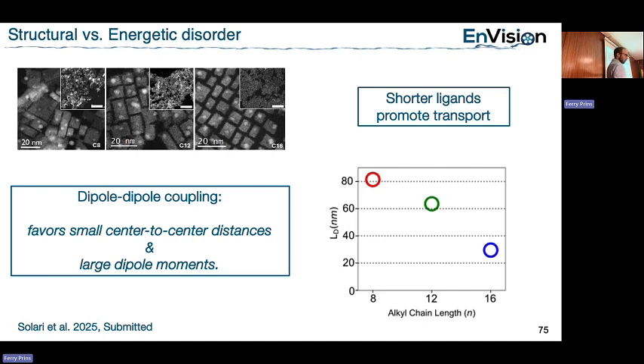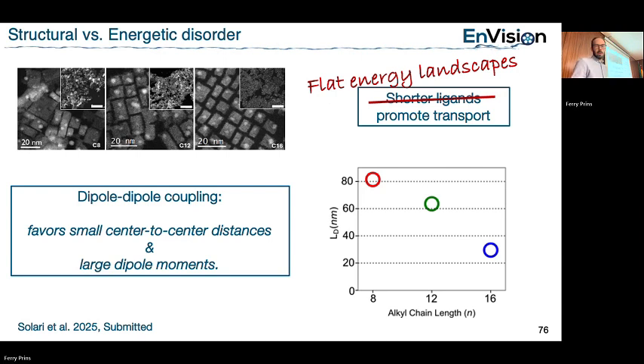It doesn't. So while the easy conclusion would have been, yeah sure, if you actually go into all the detail, you see that things are more complex. And if you want to optimize your system, you should not go to shorter and shorter ligands. You should go to a system that has the most flat energy landscape. It's a different parameter that you need to optimize if you want to optimize transport.